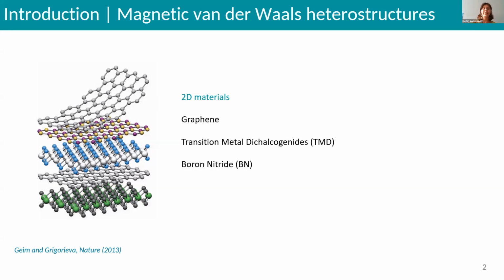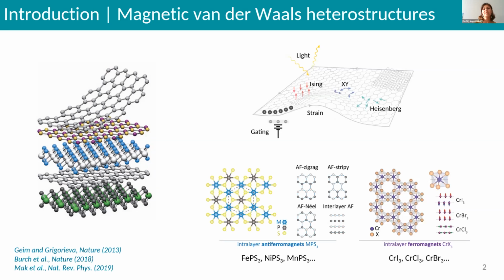But recently, a new part of this van der Waals study has gained some interest. In 2017, the persistence of a magnetic order in a monolayer of magnetic van der Waals material was demonstrated, offering the possibility to embed the magnetic degrees of freedom in these van der Waals heterostructures. So since then, a vast catalog of van der Waals magnetic materials has been studied, possessing a great diversity of magnetic order. For example, the family of FePS3 and MnPS3 are antiferromagnets, whereas the chromium trihalides are ferromagnets. In this family, you can also find different spin orientations, in plane or out of plane, that can be described by theoretical models like Ising, XY, or Heisenberg.